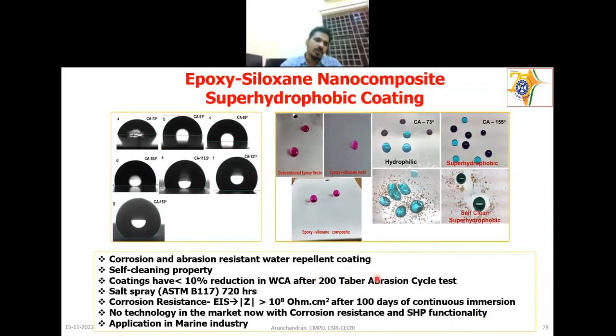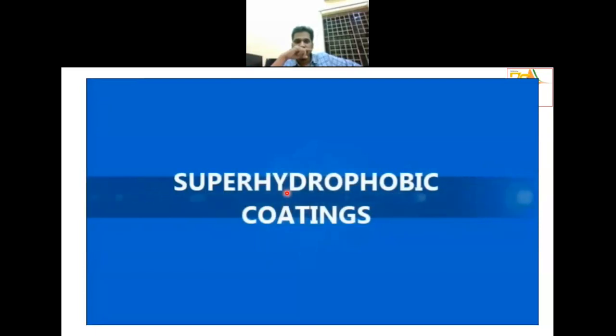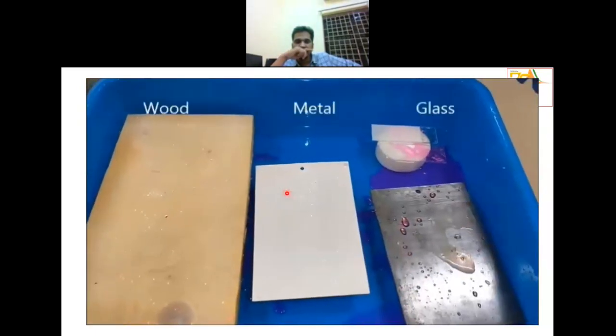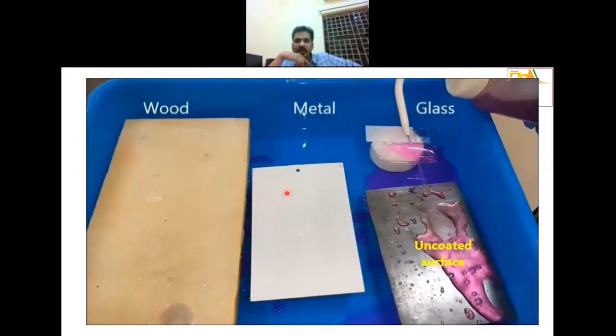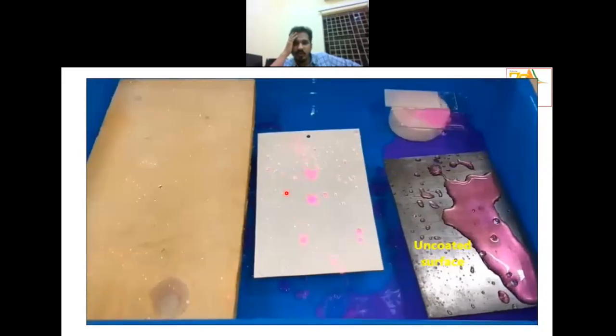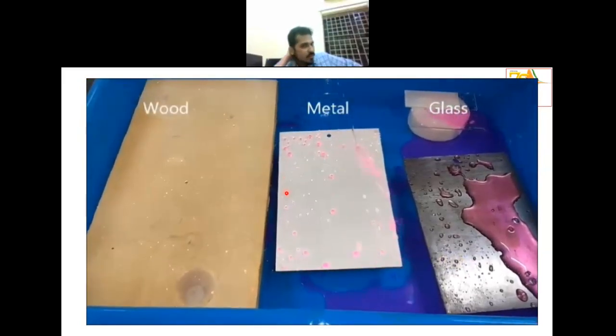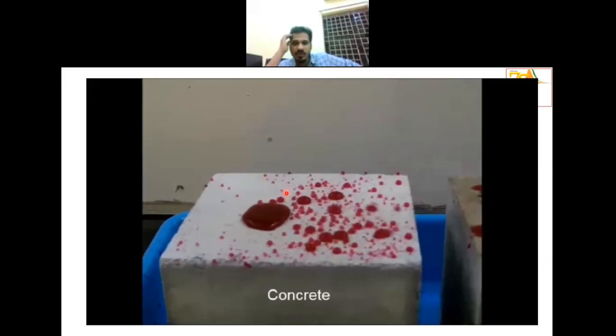There is another coating, the epoxy siloxane nanocomposite coating we prepared, and this also shows super hydrophobicity. We made various combinations, and this one also has a pattern we applied. In this epoxy siloxane coating, we added various pigments to impart the super hydrophobic function. I will show you one video here of how this coating is really working. This is the uncoated surface. When we pour water on the metal surface, it is freely rolling off here. And this wooden surface is also coated using the same thing. You can see it is bouncing off, and it's the same on the concrete substrate.